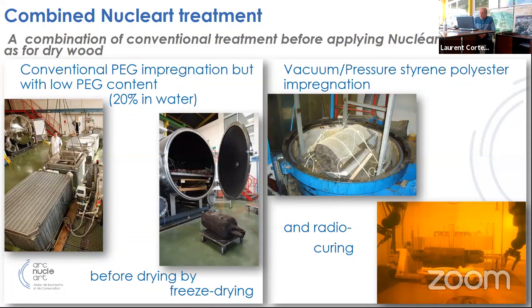That's why we now use a combined treatment. The idea is to use conventional PEG and freeze drying, but with minimum PEG content to dry the artifact before we can fill the remaining porosity with classical vacuum pressure impregnation of styrene polyester, as we do with dry artifacts, and harden it as usual by gamma irradiation.